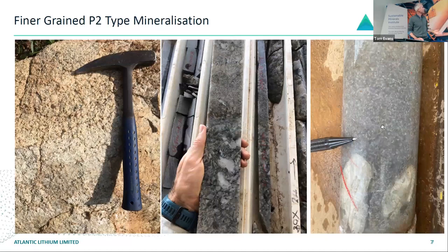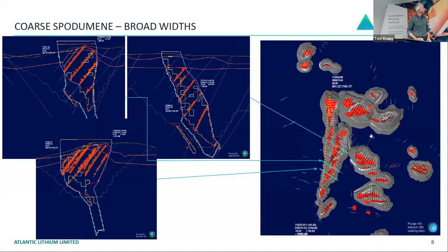But from a processability point of view, this is much harder to process to a saleable concentrate than the coarse grain material. And depending on how much of that you've got volumetrically would really dictate how you have to process this material going forwards. You could go into flotation at a much higher cost, or you can still generate a saleable product through a dense media separation circuit.